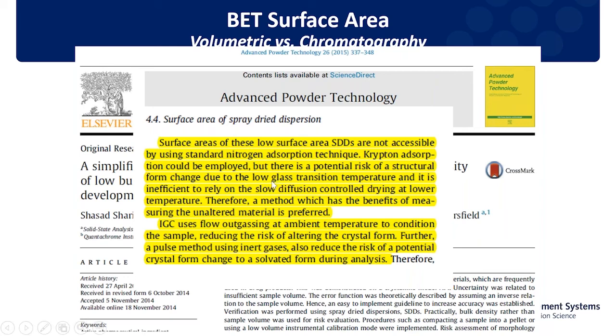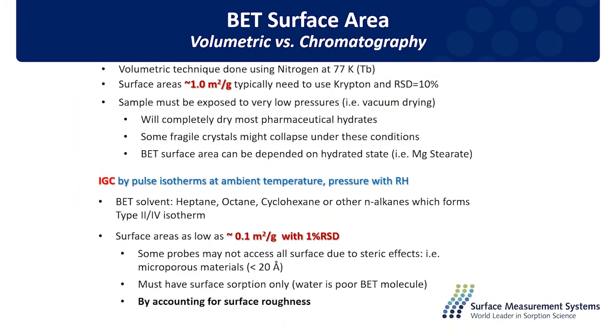In that case, because the spray dry dispersion has a low glass transition temperature, it goes through structural changes when you cool it down to the measurement condition of the nitrogen sorption measurement. IGC they suggest as an alternative method because it uses ambient temperature conditions, inert gas flow, and pulse injections. All this reduces the risk of structural changes. So with IGC, using different organics, you can measure the BET specific surface area, and the accuracy at the low surface area range is much better than the nitrogen sorption measurements.